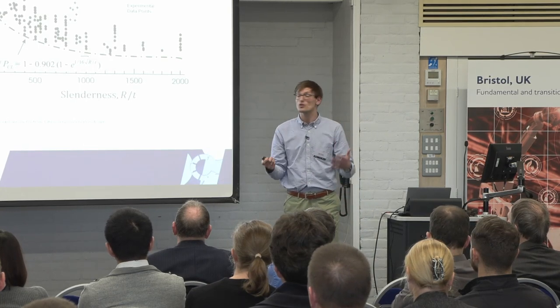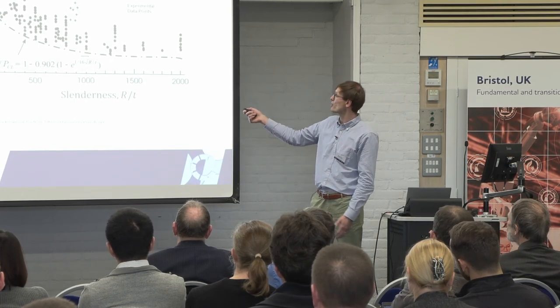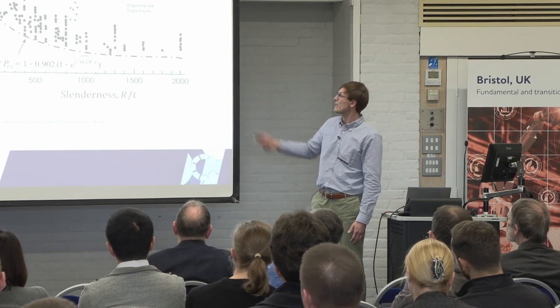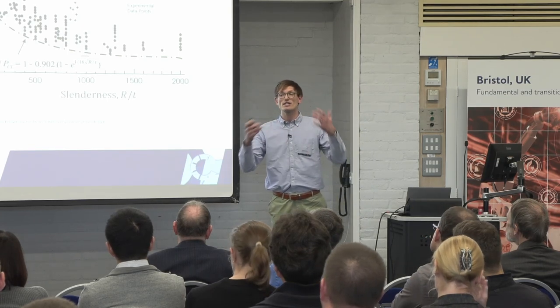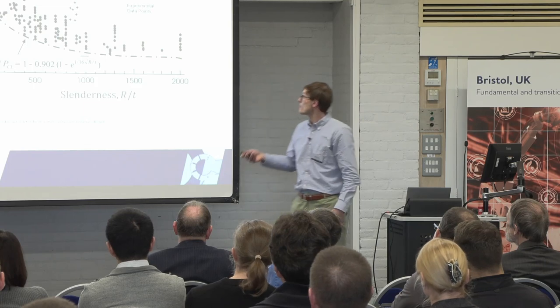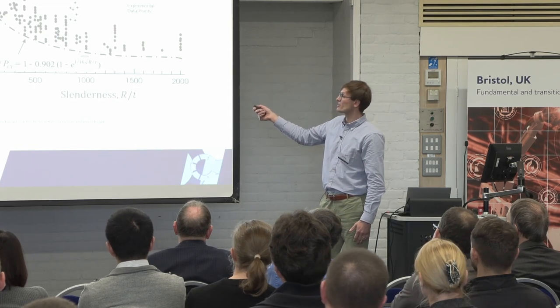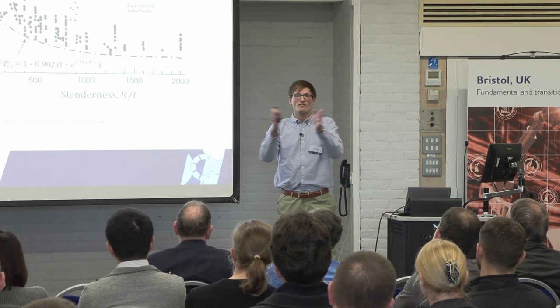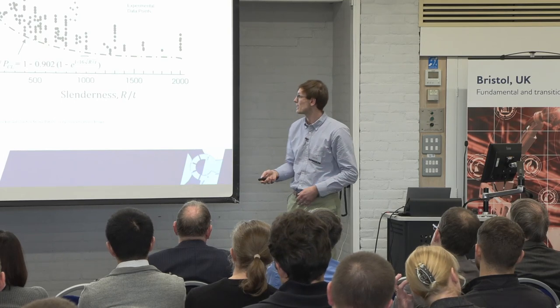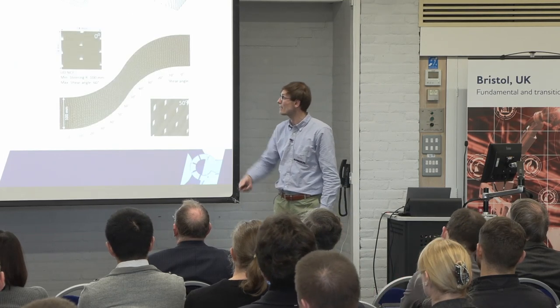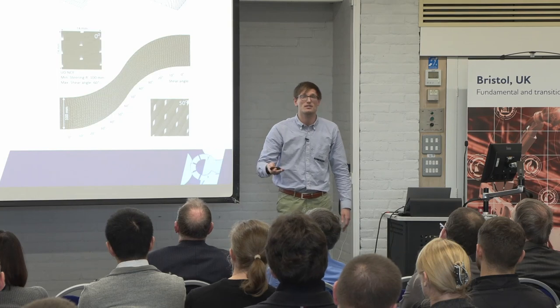So what we tried to do is essentially ask the question, can we push up this lower limit a little bit? Can we increase the worst case scenario? But also, can we minimize some of this distribution? Can we shrink the variance that we would expect in experiments? And the way we did that is with the rapid tow shearing process.